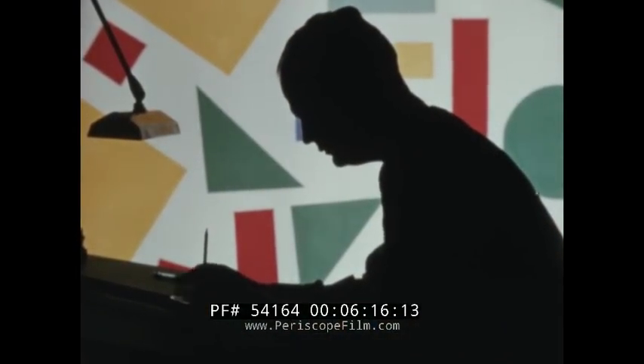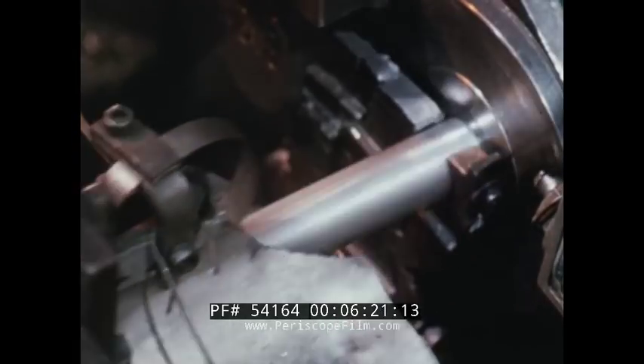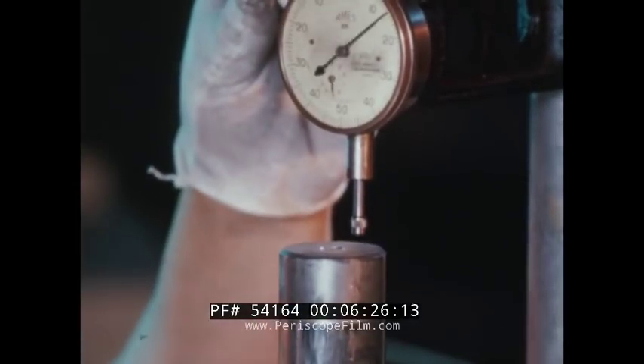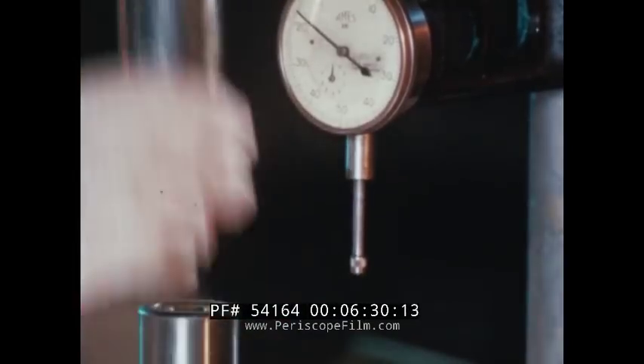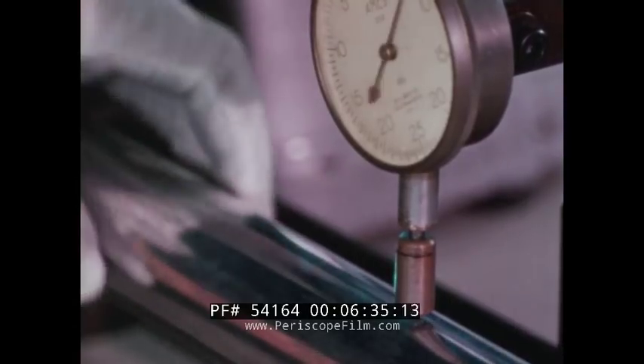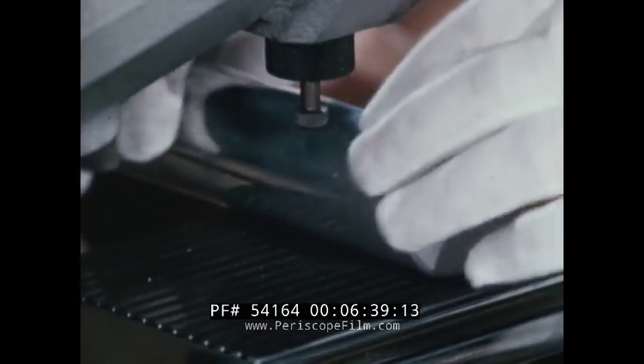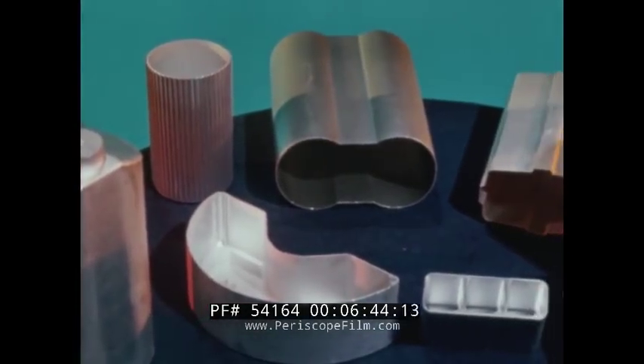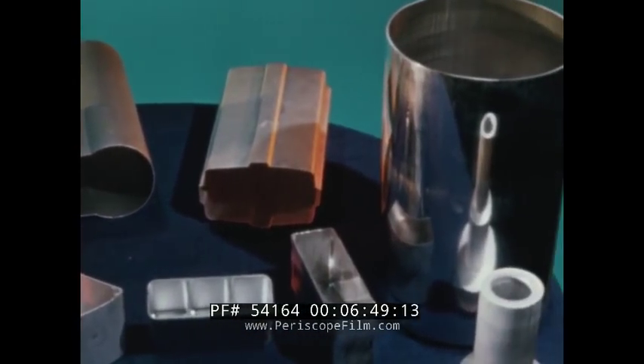Now about tolerances. If this is a critical factor in your design, keep this in mind: the inherent accuracy of the process permits cross-sectional tolerances down to plus or minus two thousandths of an inch. Walls and other surfaces are draft-free. An Alcoa impact will require a minimum of machining. And since there are no parting lines, no joints, the smooth, bright surface is close to a final finish.